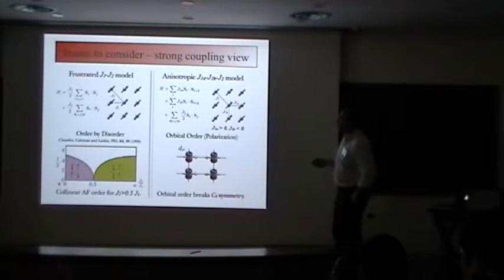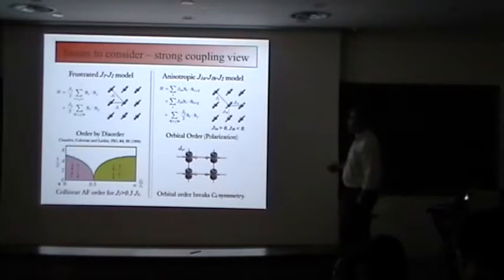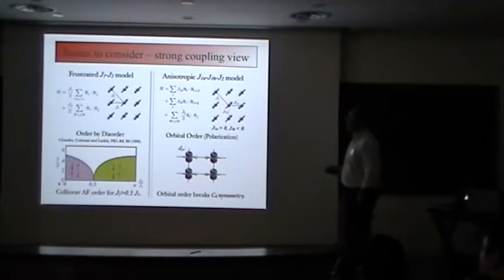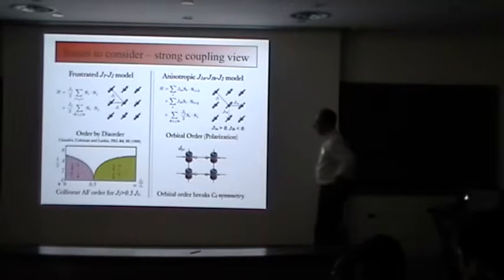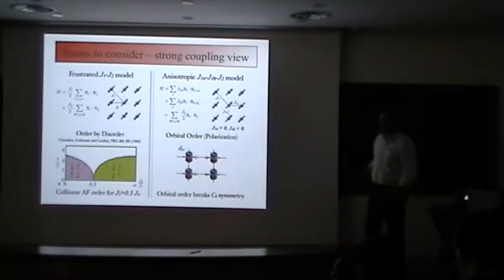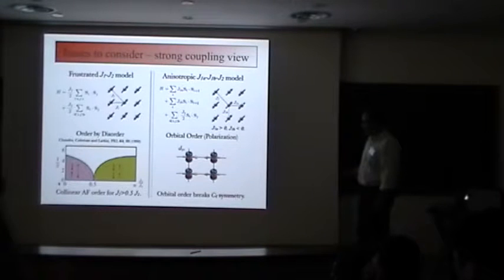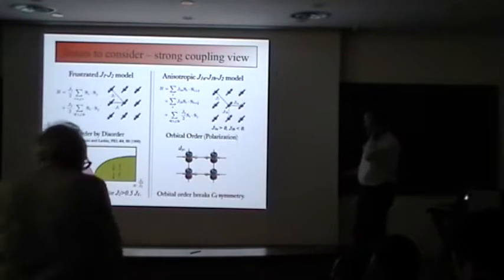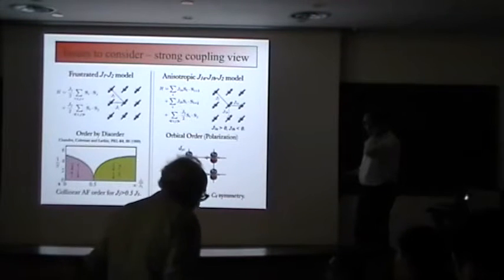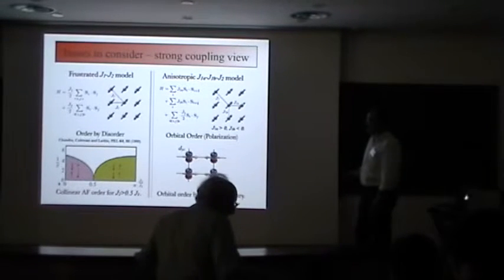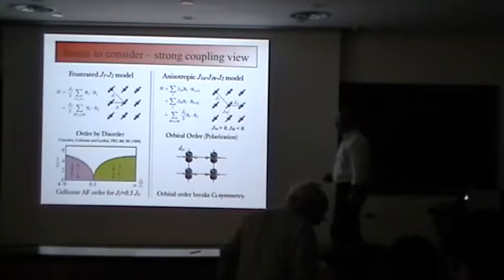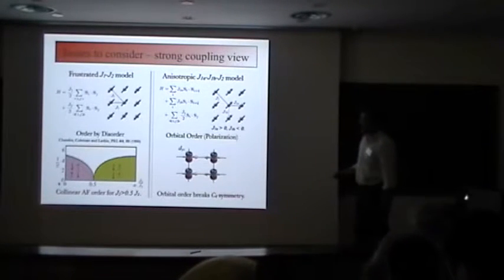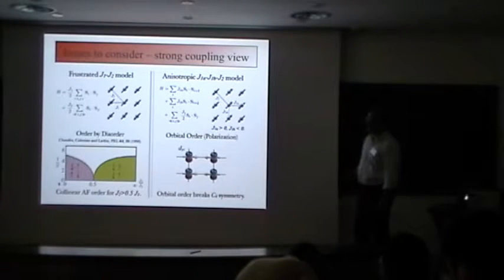So one particular way of looking at it is to take an extended Heisenberg model. Here's two that I've written down, which has a nearest neighbor exchange between effective spins sitting on the iron, and the next nearest neighbor exchange J2. One way the moment can be controlled is by looking at a quantum critical point, a so-called order by disorder effect, where if J2 is on the order of half J1, that separates two competing phases: a checkerboard antiferromagnetic order from a collinear antiferromagnetic order, with critical points sitting in between when the fluctuations become very, very strong.